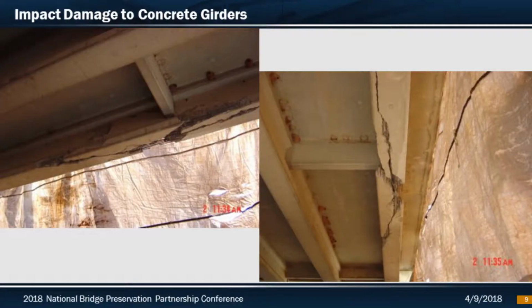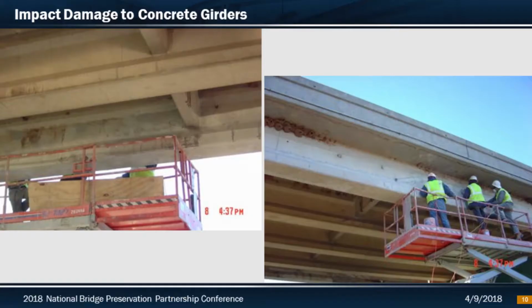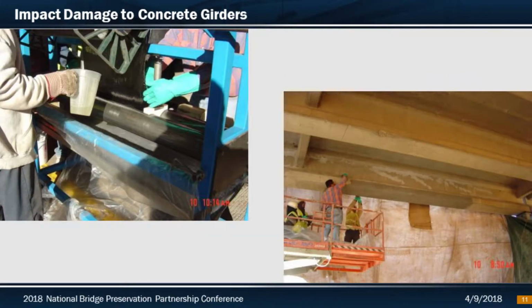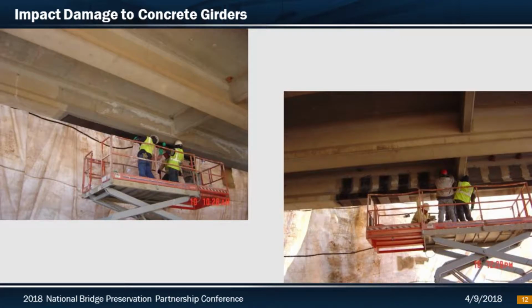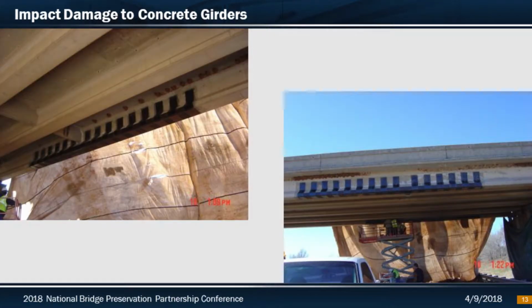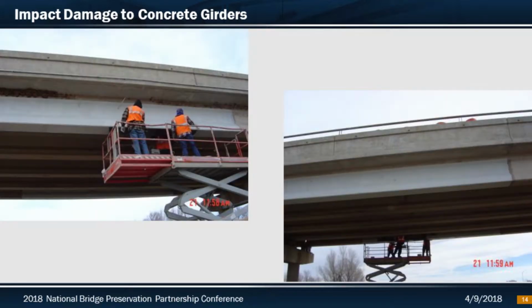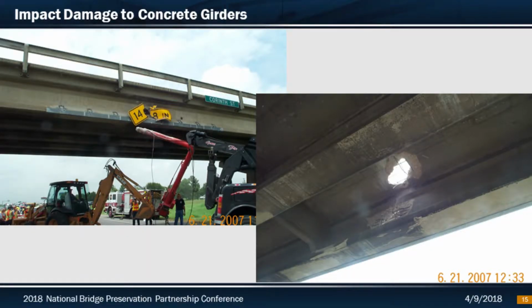Amarillo, on an interstate, over the interstate, again another damage that would have been a complete beam replacement. It was repaired with concrete patching, epoxy injected into the cracks, and then repaired with the CFRP wet layup. The saturator, as was mentioned earlier. So longitudinal, and you can see on the next slide the U-wrap strips on the bottom flange up through the girder web. Here they are, kind of the complete product. Then when you get to the final, we put the top coat on for the UV protection again, as was mentioned earlier.